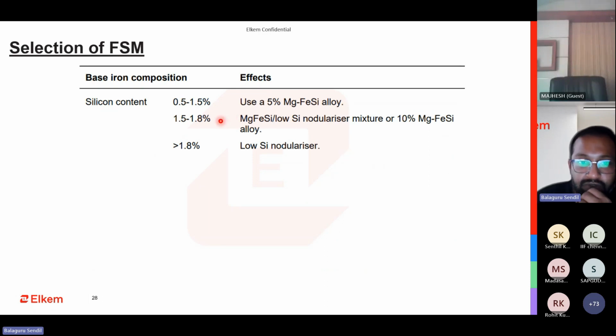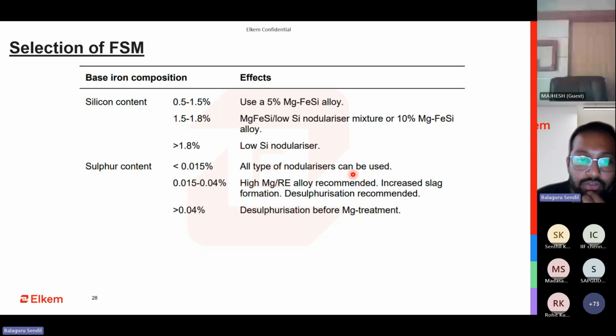Unfortunately, this is the range we will be in. So which amount of FSM you have to select depends upon your silicon. And the next is the sulfur. If your sulfur is less than 0.015, any type of nodularizer will work. And this is the one we should target. Anything more than that, we should try to control it. Theoretically 0.04 is possible, but it is very difficult to activate at 0.04. 0.03 also we can try.